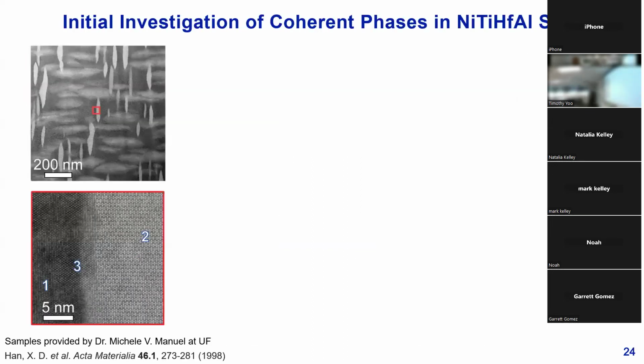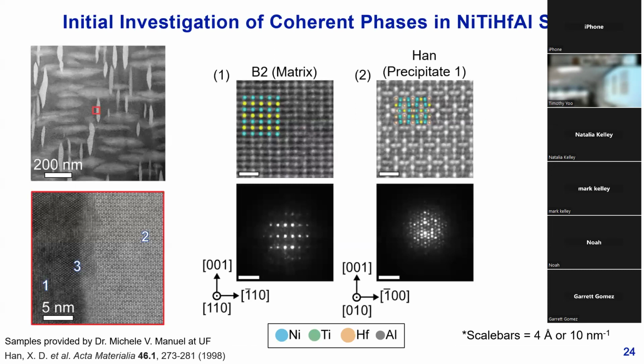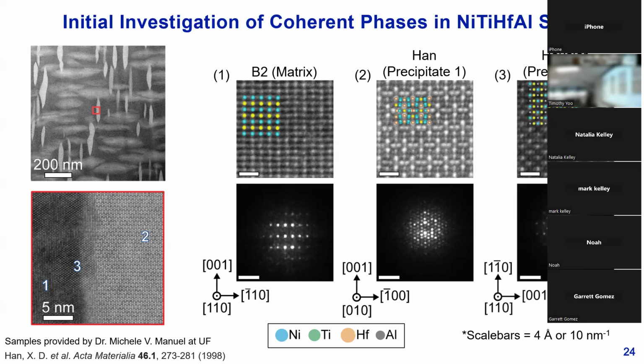But from imaging alone, we can tell a few things. Off the bat, we can tell that there are at least 3 different types of structures with unique phases that we see in this alloy. 2 of them are what we call the B2 phase on the left, and those bright needle-shaped precipitates are something called the Han phase. We just call them matrix and precipitate 1 for now. And then we also see that there's a secondary precipitate called the Heusler phase, but we'll just call that precipitate 2 to keep it easy.